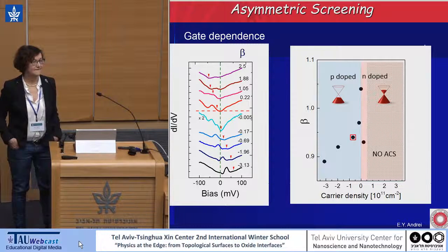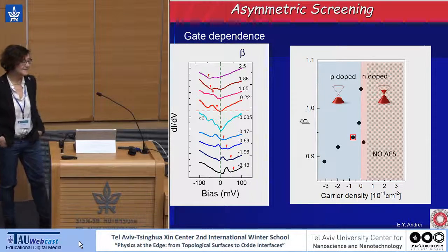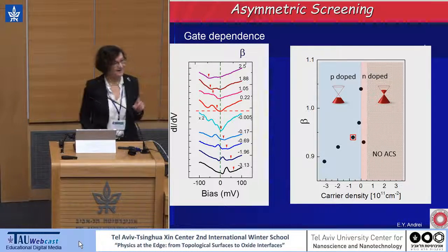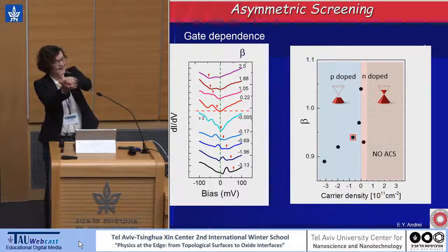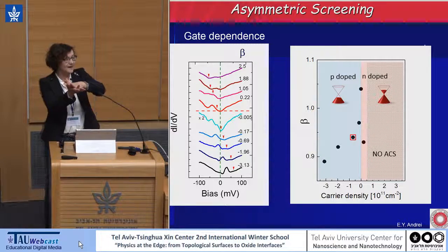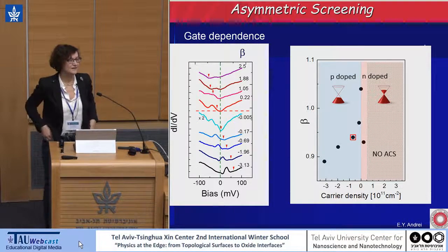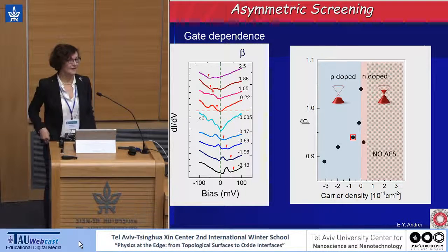Is this suspended graphene or is this silicon substrate? OK, so this is a double layer of graphene. It's not a bilayer. It's a double layer. So we put another layer at a large angle of rotation so you don't get coupling between the two layers. And the reason we do that is to decrease the amount of random fluctuations from the silicon dioxide substrate.